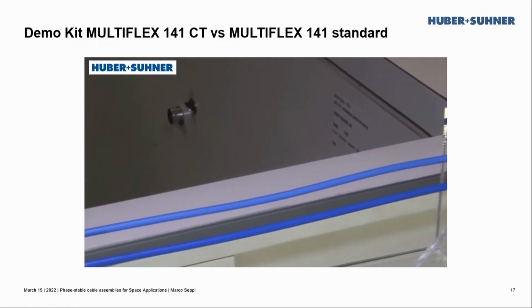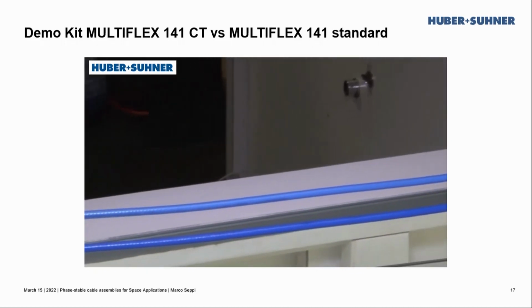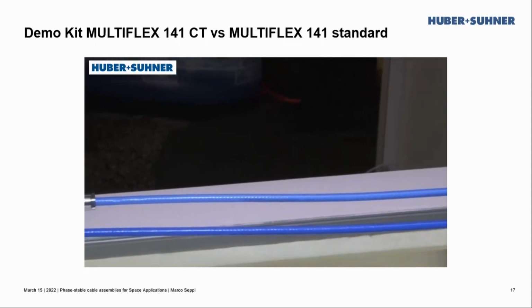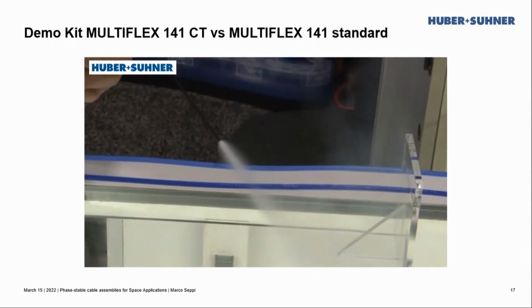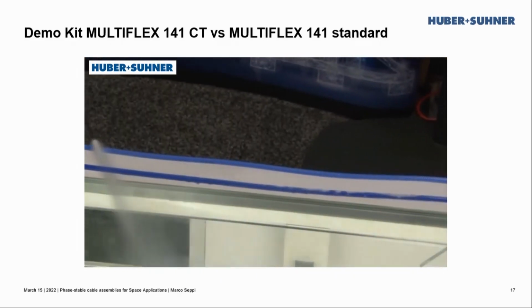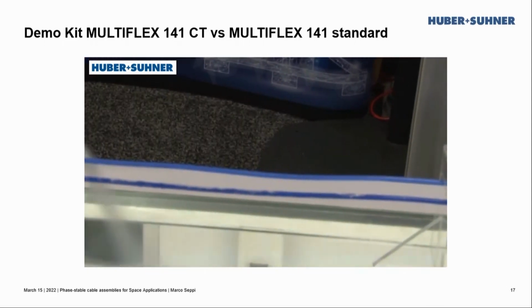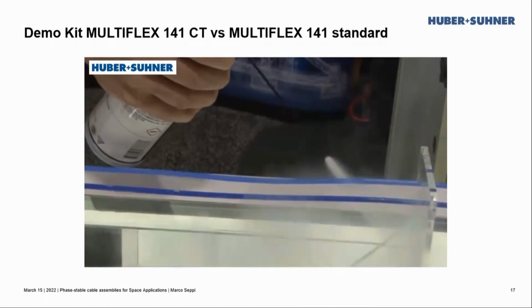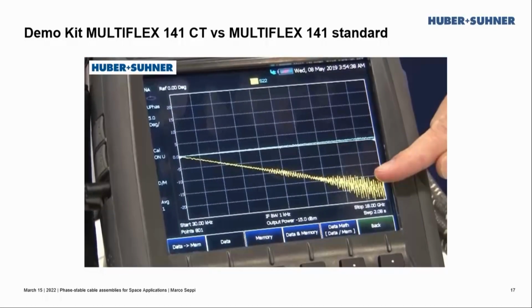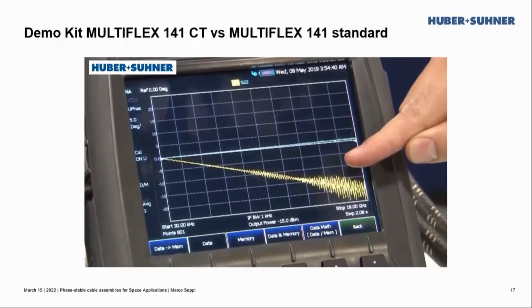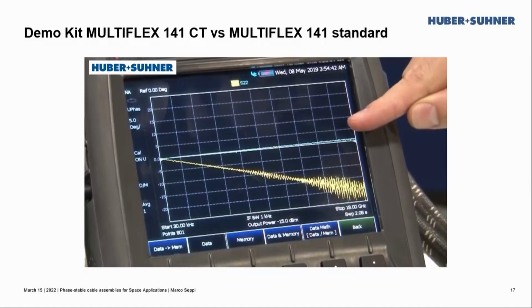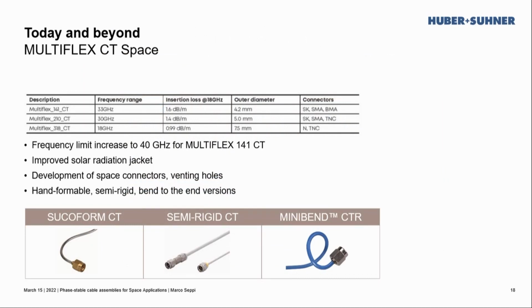Here you see how they are mounted on the stand for relative comparison. In a second, you will see the application of the low temperature spray. So we reduce the temperature to well below 0 for both cables. And then afterwards, you will see the measurement of the phase. And as you can see, while on the CT cable, the consistent over temperature, the phase remains constant, the light blue line. In the case of the standard cable with PTFE, there is a drift in the phase, and we don't ensure the reliability that we would like to have for this product. Yeah, I think we can move to the next slide.